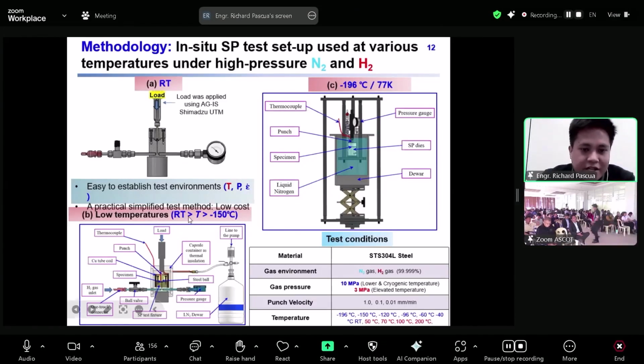with the corresponding temperature range, we utilize liquid nitrogen to cool down the specimen inside the die, and we use a capsule container as our thermal insulator to prevent heat loss and easily maintain the test temperature during the test. We attach a thermocouple on the specimen surface to monitor its temperature, and we conducted the test after the temperature stabilized within 10 minutes. At cryogenic temperature, we simply submerge the die into the liquid nitrogen, and after stabilizing the temperature, we conducted the test.